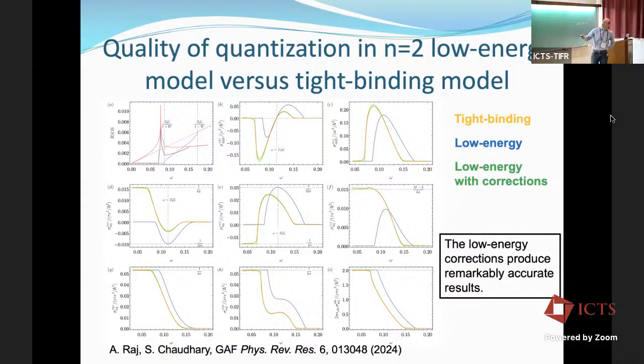And so what I think is particularly dramatic here is that if you look at the orange and the green, which is the full theory, tight binding, and just the low energy corrections to that idealized Weyl point, they basically lie right on top of each other. So the first corrections actually give you very significant agreement with the full band structure. So that's potentially very useful in making comparison with experiment.